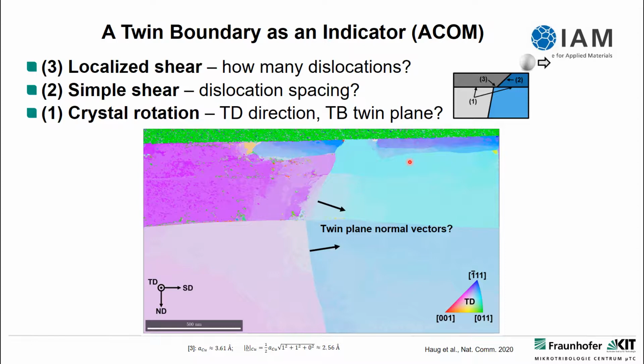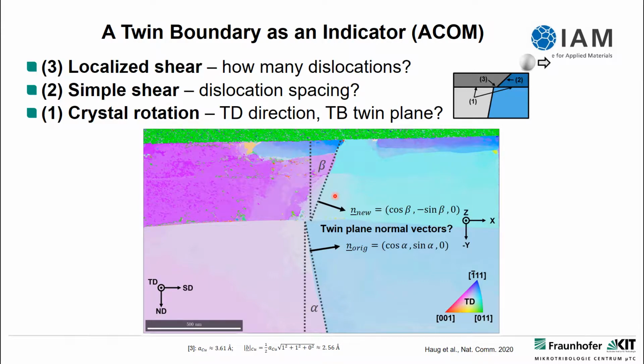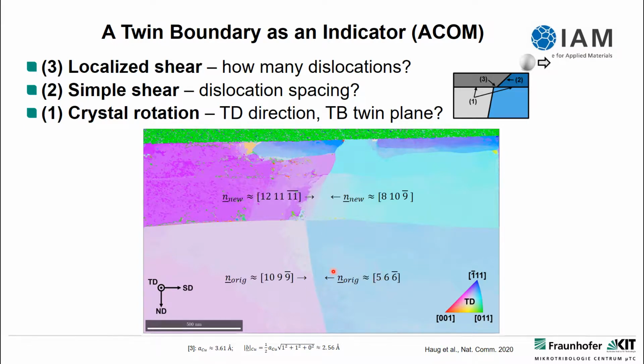The way to look at this is to examine the twin plane normal vectors. We can figure these out from the ACOM data, both below and above the trace line. Let's look at them and see what that is. So we see the twin planes, these are the vectors of the normal vectors of the twin, and we can do this from the left and from the right.